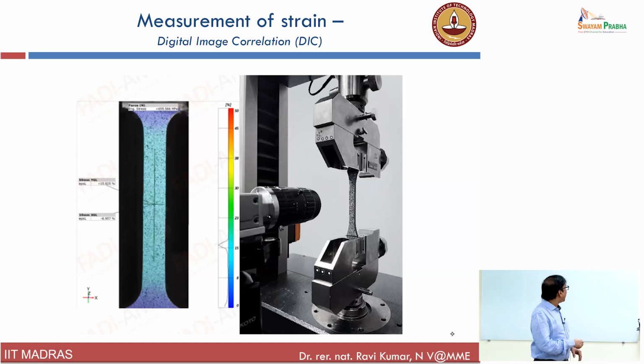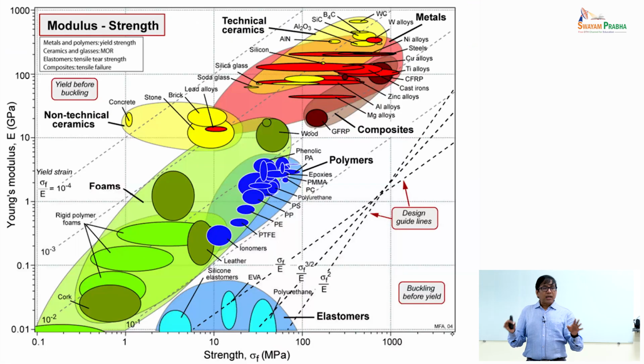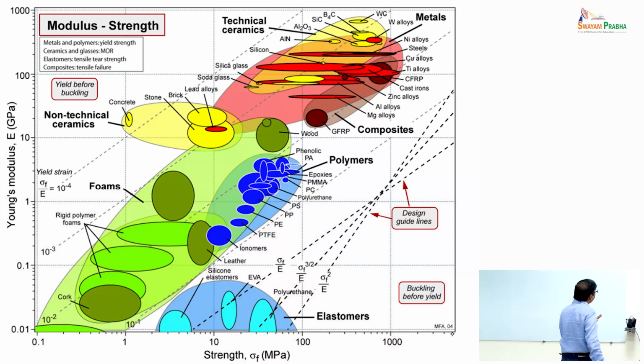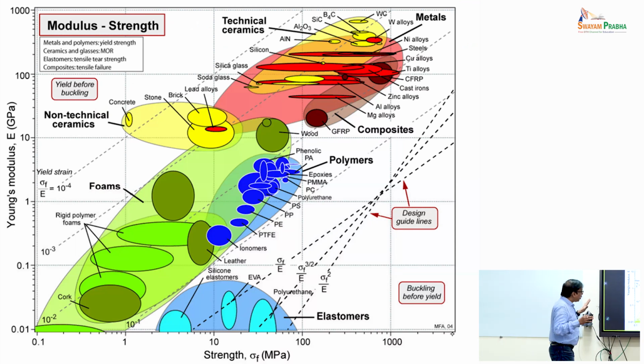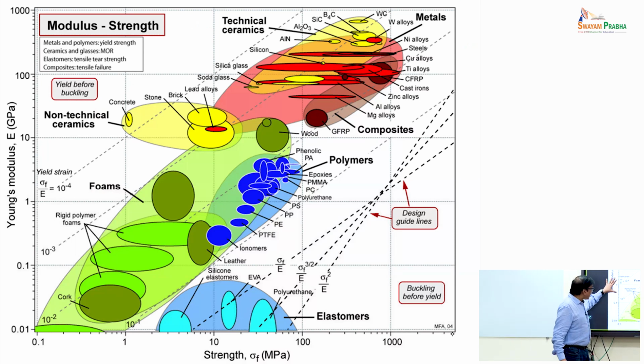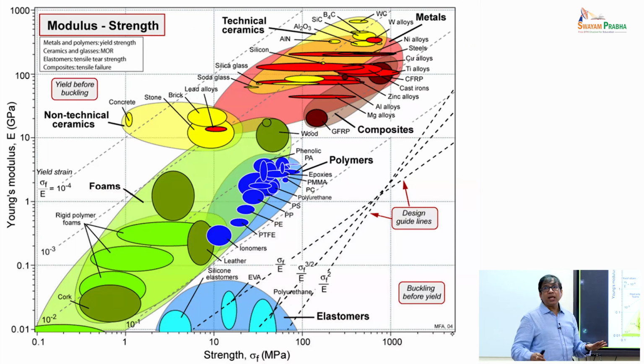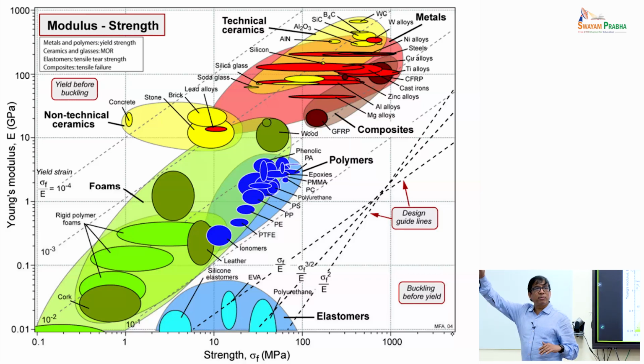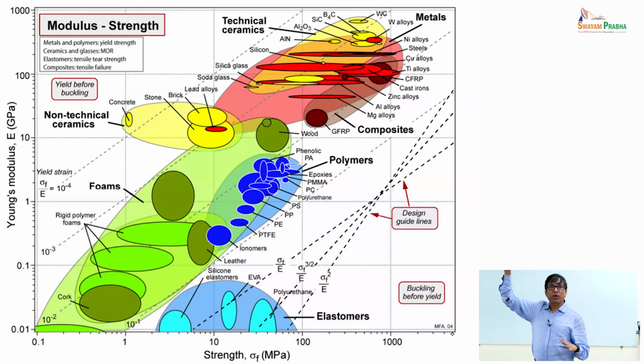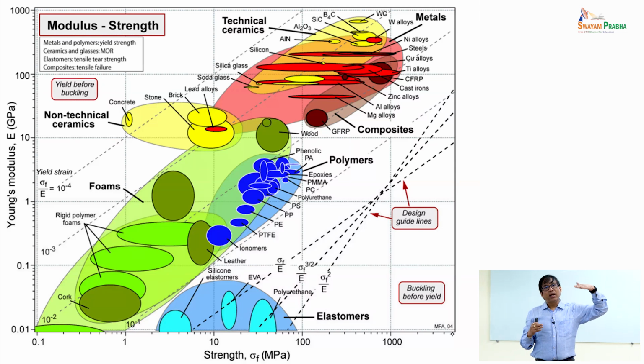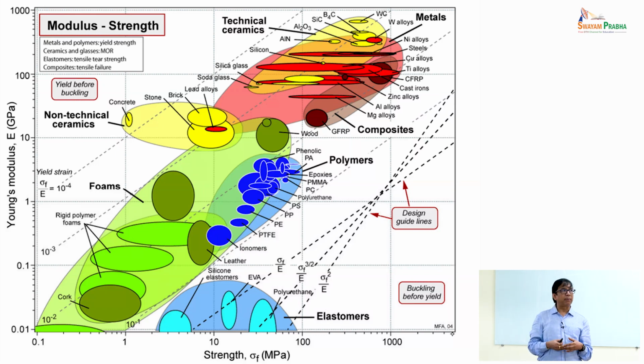So, challenge. Yeah. So, this is the kind of challenges that we actually face. And for people to get a rough idea of where we stand, this is Young's modulus as a function of strength. Obviously, technical ceramics will be on the top right-hand corner, because their Young's modulus is high and strengths are also high. In fact, the typical compression strengths of ceramic samples will go up to almost a few gigapascals, and Young's modulus is always in the order of gigapascals.